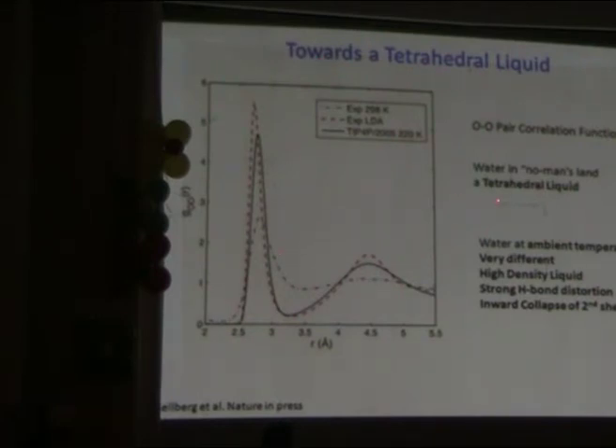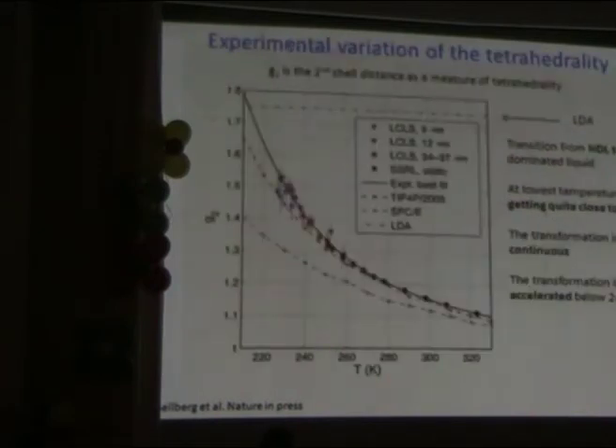Well, people normally speak of ambient water as tetrahedral. Here's the pair correlation function for ambient water. Here's the pair correlation function for low-density amorphous ice. And here is TIP4P 2005. It's a simulation at 220 Kelvin. And 220 Kelvin is where we have to go in the simulation to correspond to the G2 of the experiment.